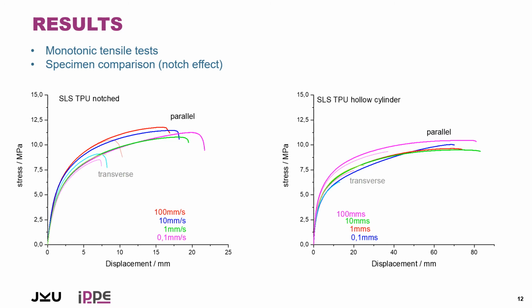These monotonic curves can be used for phenomenological modeling. Does it mean we can determine modulus values? We determined also Poisson's ratio values. We determined tensile strength values, and these curves can be used for elastic plastic material models. And hence, we performed rate-dependent tests from 0.1 to 100 millimeters per second. We were able to determine material model parameters for elastic viscoplastic material models.